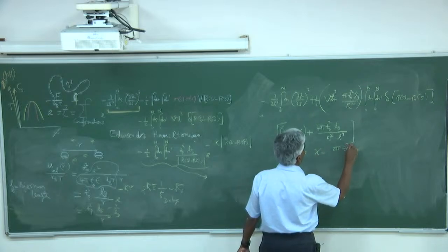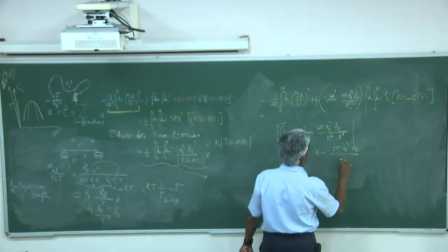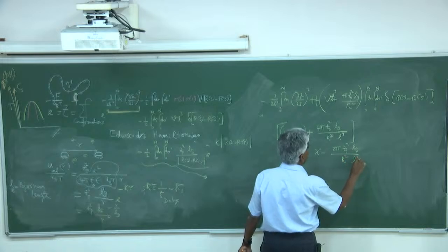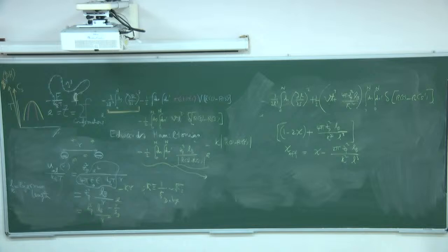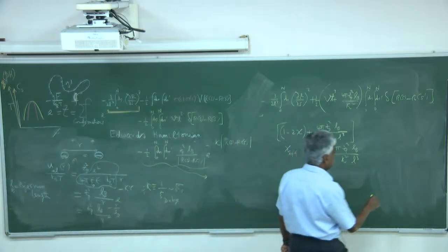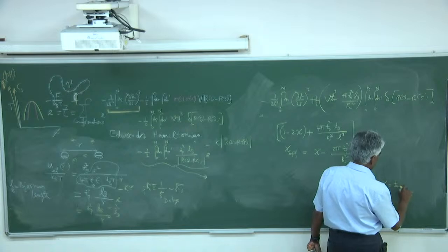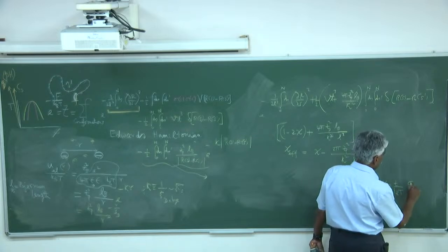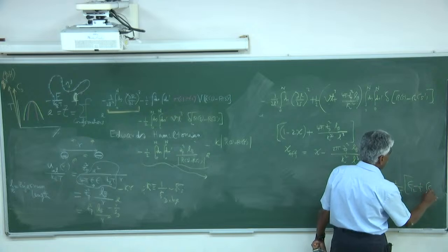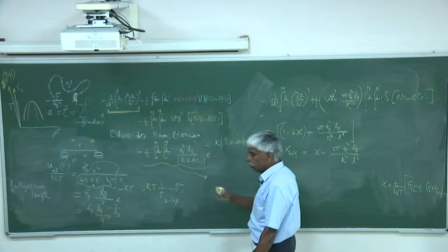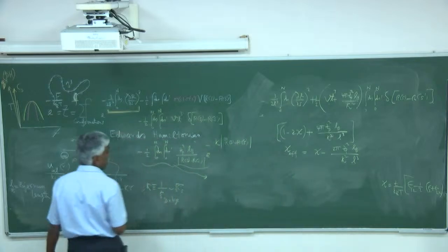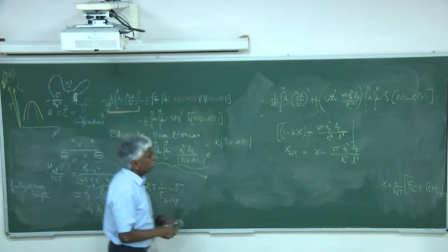Remember, chi is like 1 over temperature. So by adding salt, I am dramatically changing the effective value of chi. Remember in the phase transition, liquid-liquid phase separation, I told you if chi is sufficiently positive, it will phase separate. So I can adjust the phase diagram with the salt, and Mother Nature does that.